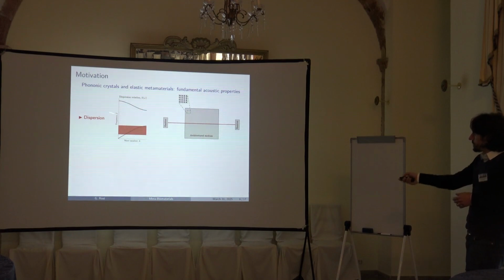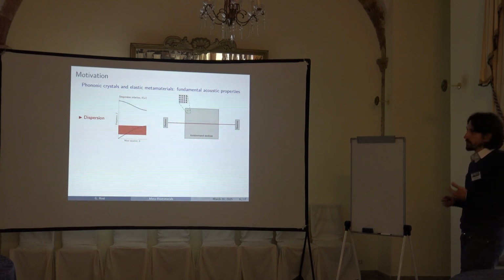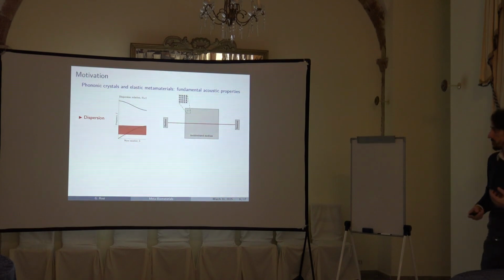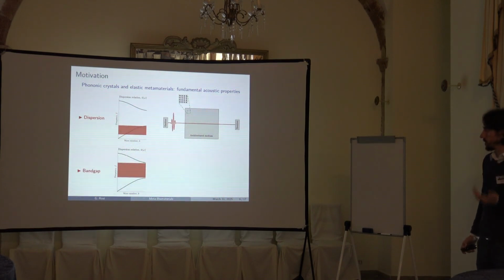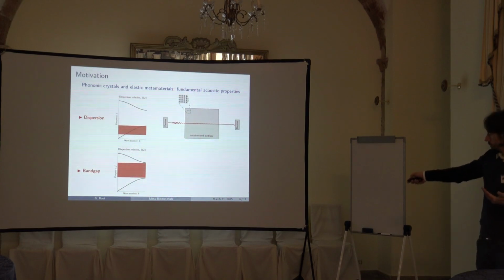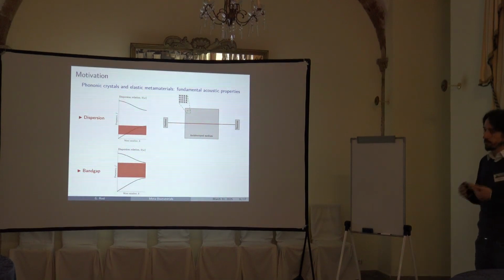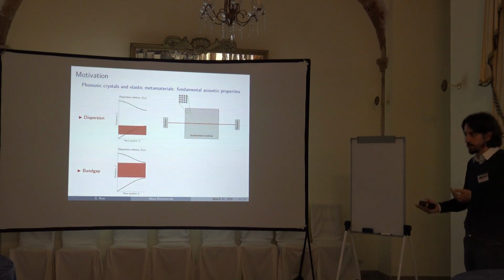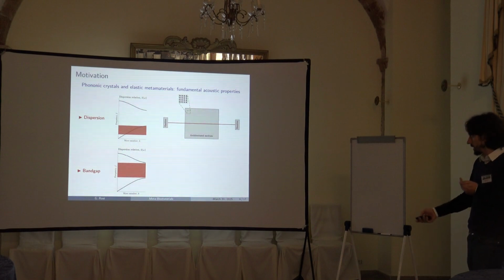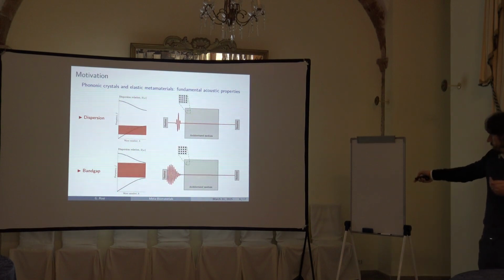If you go upper in this region where there is no black line, meaning that there is no purely linear solution for wave propagation, you have a very well-known phenomenon, which is called bandgap, which means that when you excite a wave that has a frequency in this region, you will not have propagation inside the specimen. This doesn't mean that the wave will be damped. It means that it just cannot propagate. So in our configuration, you can see that the signal is emitted and just cannot enter the material.